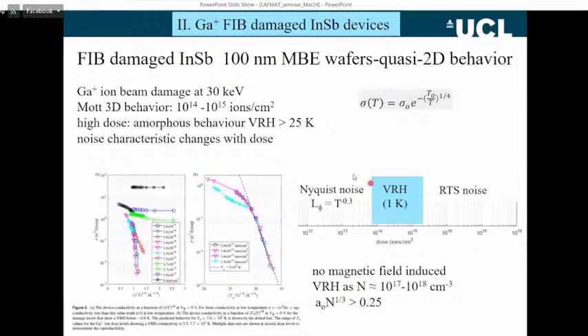And so for low dose, what happens is in the device, we have a kind of a Nyquist noise going on in the system. So that's kind of an inbuilt electronic noise. And that's the kind of scenario we wanted to be able to study this variable range hopping effect without phonons. So if we take away the phonons from our suspended layers, can this Nyquist noise, this kind of fundamental electronic noise, create a hopping effect? So that's what we were hoping to see.